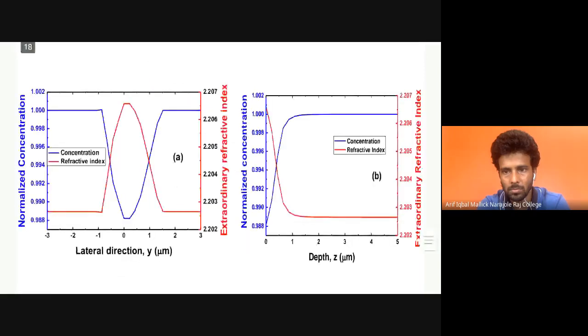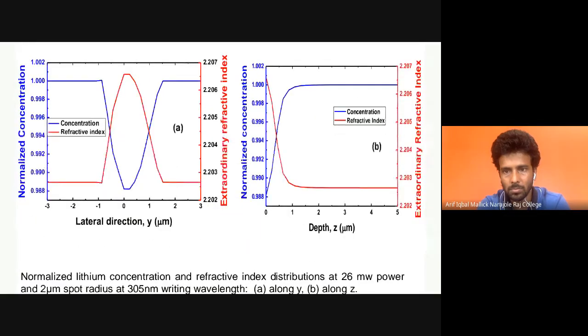Finally, we obtain the refractive index profile along the lateral direction and depth direction. The blue curve indicates the concentration profile, and the red curve indicates the extraordinary refractive index change. But from this figure, we observe that the full width at half maximum is about 1.5 micron, which is not experimentally supported. That is very small compared to the experimental result. We have to obtain the actual full width at half maximum by optimizing the activation energy.